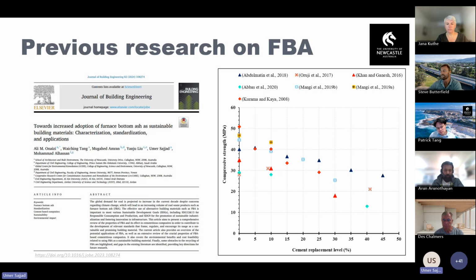Because compressive strength is the major, or you can say the most important parameter which we use to determine the characteristics of concrete. So in this slide, you can see although the replacement level goes up to 45%, the strength is significantly reduced if we use furnace bottom ash as SCM or sometimes with fine aggregates, but up to a replacement of 5 to 10%, the strength is not that much reduced compared to the control concrete.